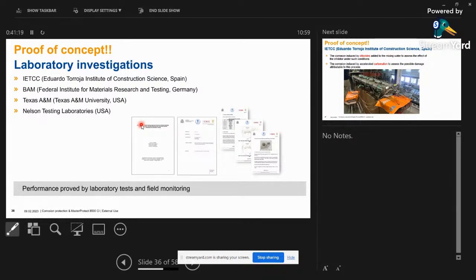Now, once you apply it, there is a mechanism, there is a process. All corrosion monitoring mechanisms are such that you don't see the result immediately. You have to wait for some time and observe it over a period of not less than 6 months to 1 year, basically beyond 6 months. You have to keep monitoring it, and then you see all the deliverables start to fall in line, the corrosion activity starts to reduce, and concrete resistivity goes up. All those effects are quite visible as you monitor it over time.